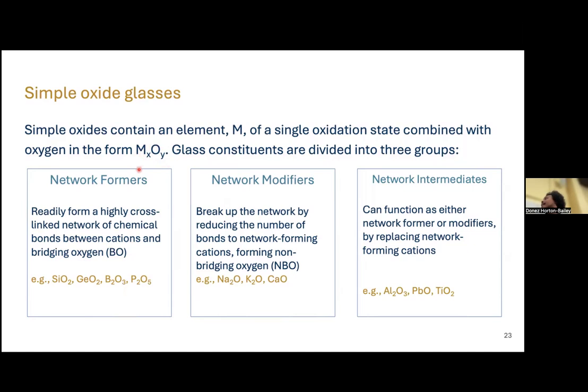But for the simple oxides, I'm able to classify them into 3 categories. So the first is network formers. This is the typical glass that we work with. It's easy to supercool the liquid into a glass. So silicon dioxide is the main one there, but there are some other examples down here. We have network modifiers. You can introduce these into a glass, and these actually break up the network. It breaks some of the silicon-oxygen bonds and lets the oxygens hang. Typically in a pure silica film, oxygen has 2 bonds. Adding a modifier breaks some of those and lets some of them have 1 bond. Network intermediates are in between. They can serve either case.